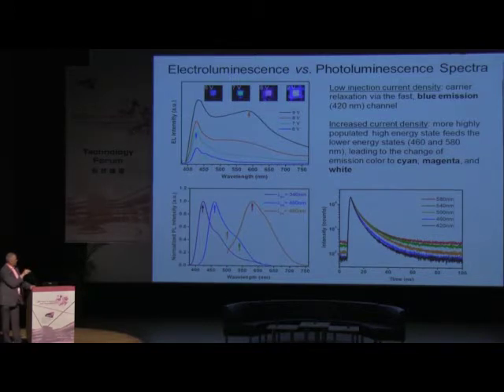So what happens here is that if we increase current density, then we address higher energy states in carbon dots. Those higher energy states can feed the lower energy states, and by that we add emission of other colors, like 460 nanometers, which is here, or even longer wavelengths, 580 nanometers, if we increase current density. And by that we change the neat emission color of those devices from originally blue to up to the white color. If we combine orange and blue, we end up with white.